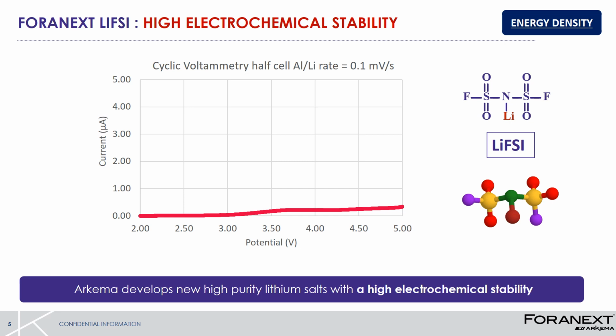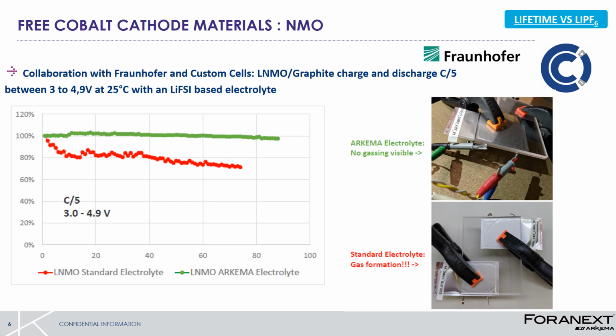For the LiFSI, Arkema developed an industrial process in order to manufacture high-purity LiFSI. In the literature, you can find a lot of conflicting information about the LiFSI electrochemical stability. Thanks to our process, results are shown on this voltammetry graph. Our LiFSI is stable up to 5 volts without any aluminum corrosion. Thanks to its high electrochemical stability, LiFSI can help the development of cobalt-free cathode materials. In the frame of a European project, an electrolyte based on LiFSI has been developed to improve the lifetime and reduce the gassing during the cycling.